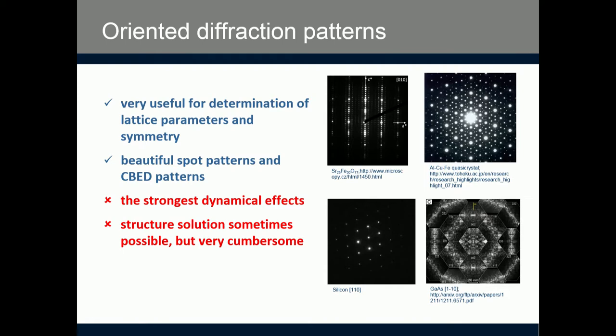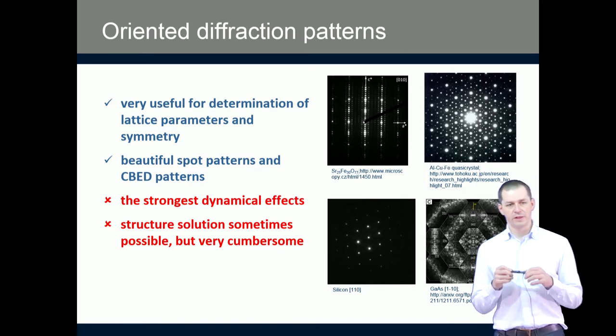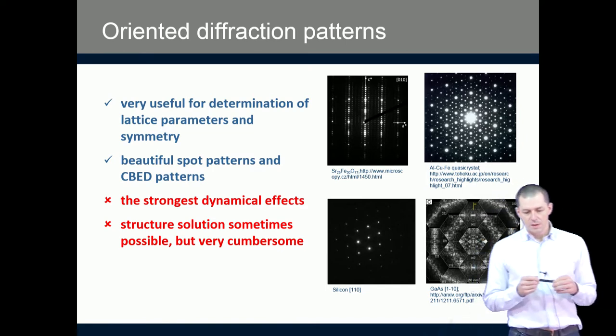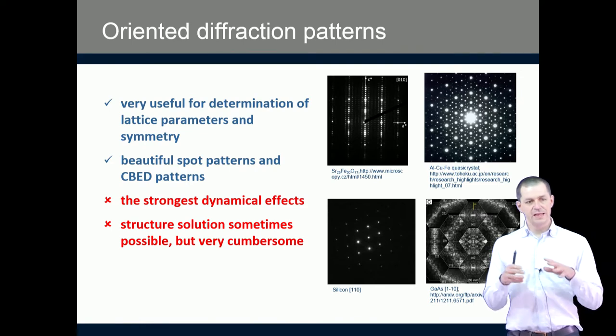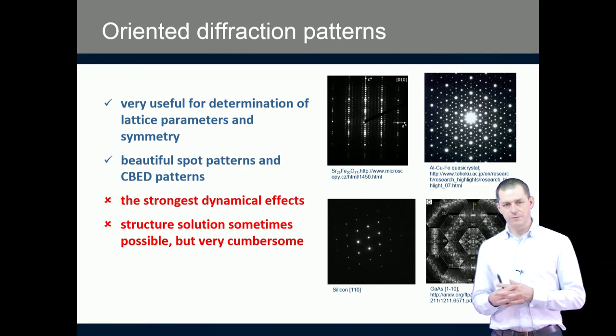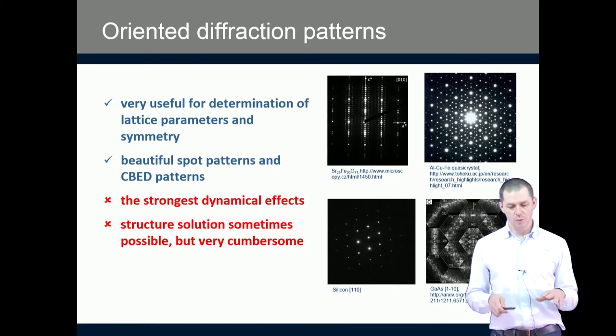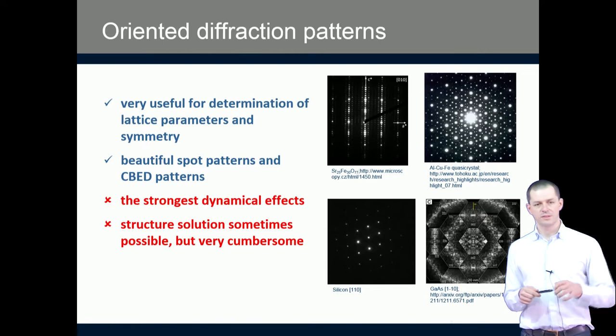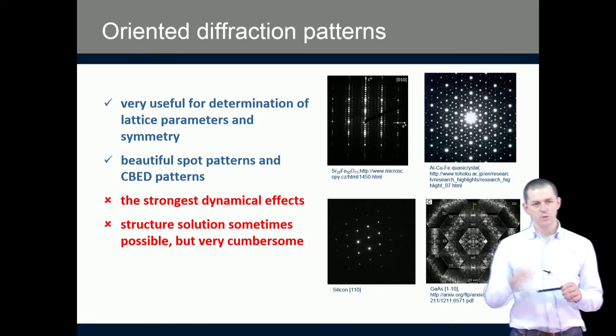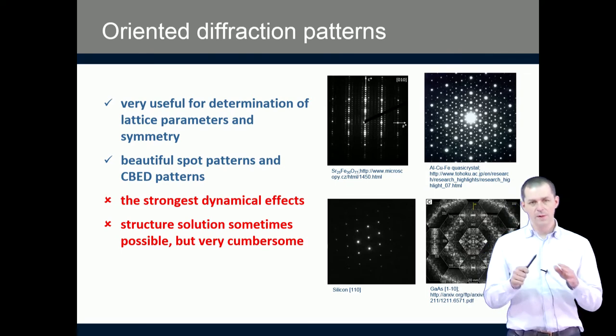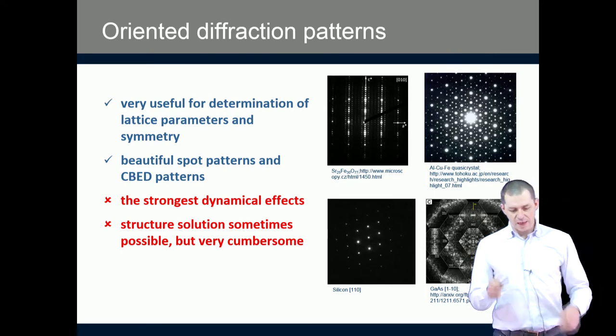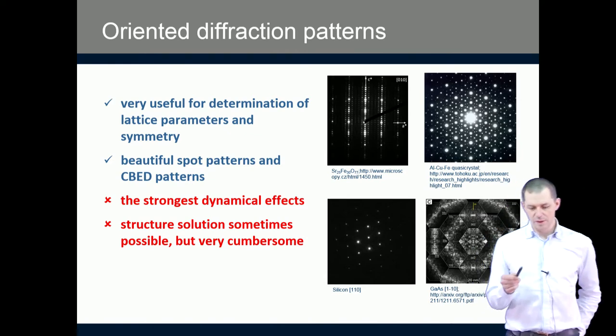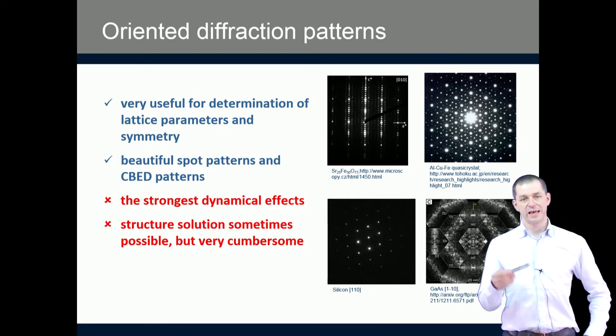Traditionally, electron diffraction has been performed mostly in the form of oriented diffraction patterns. The reason for this is that in electron diffraction, unlike X-ray diffraction, a single diffraction pattern provides you essentially undistorted planar section through reciprocal space. So if you take a single diffraction pattern, it gives you a single plane in reciprocal space, and if you properly orient your crystal, then this plane in reciprocal space will contain a lot of interesting and easy to interpret